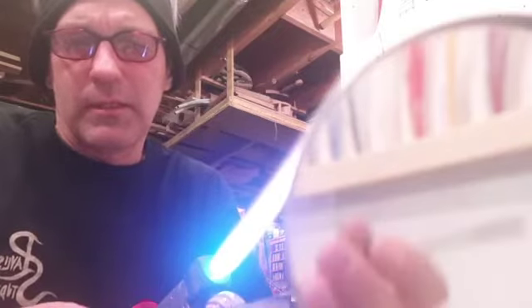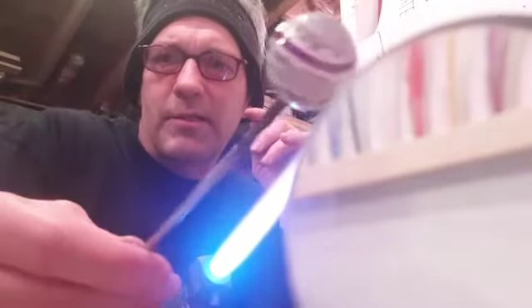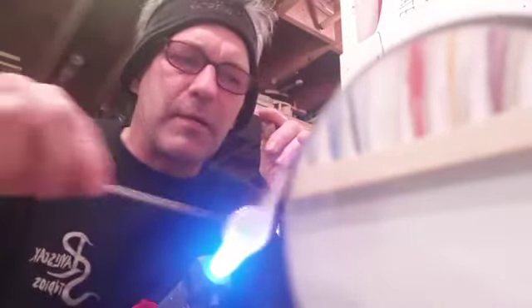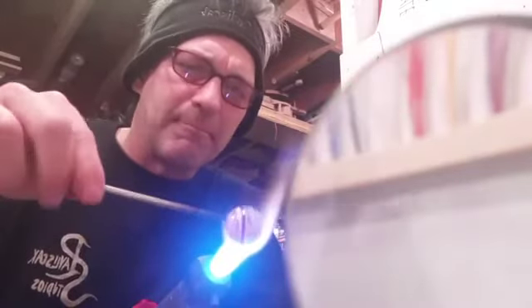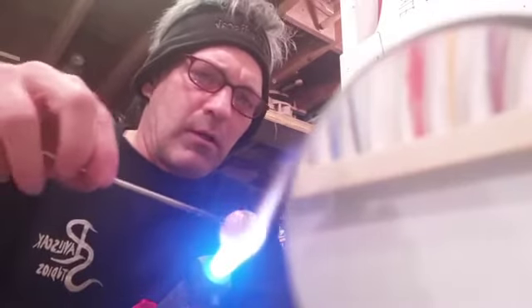Let's have a little roll around the marble molds and see where we're at. So, looking pretty good. Twist is nice. So it comes to a point. Let's heat it back up. The surface is ripply. The surface chilled on the graphite, but the insides were still hot. So we'll smooth out the surface, and I still do have some improvement of the shape. You can see it's not perfectly spherical.